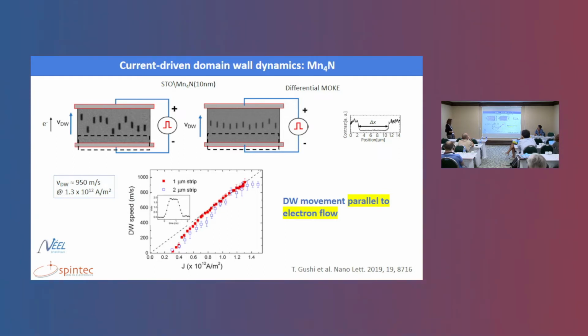Of course we change the current density, and this is the domain wall velocity versus current density. We see very large velocities, of the order of 1,000 meters per second for 10^12 amperes per square meter. For those who are in that field, these velocities are more or less of the same order of magnitude as those obtained by spin-orbit torque in systems with Dzyaloshinskii-Moriya interaction. But what was peculiar and surprising here is that the domain walls move parallel to the electron flow. So the question is, what is the mechanism responsible for the domain wall speed?